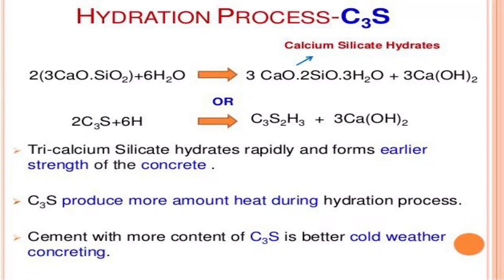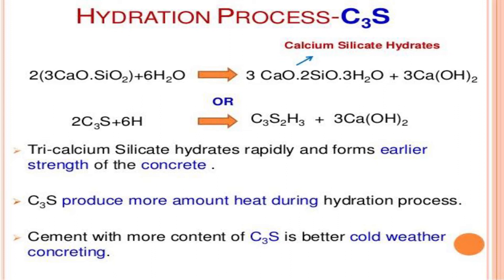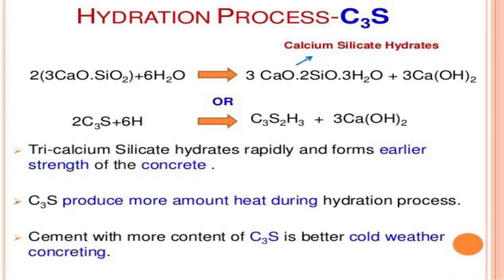This reaction which results in calcium silicate gel is an exothermic reaction, meaning the reaction takes place with the evolution of heat. Various other components from cement, such as tricalcium aluminate and tetracalcium aluminoferrite, also react with water to form hydrated components. But out of all reactions, the calcium silicate gel formation is the major contributor to concrete strength.